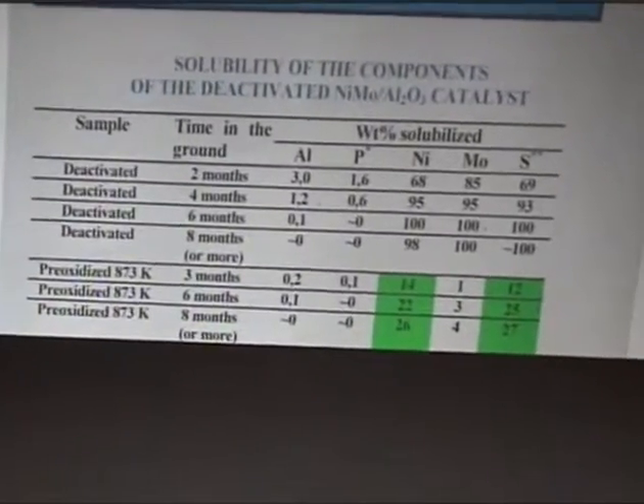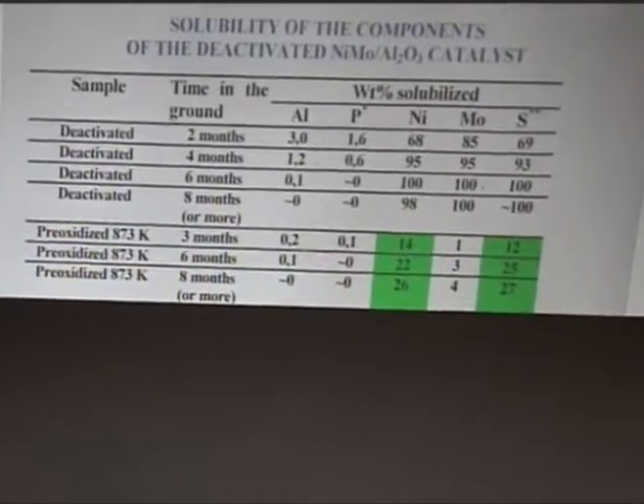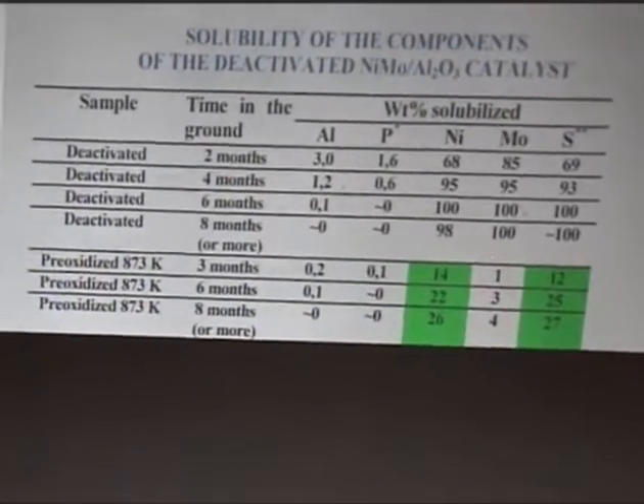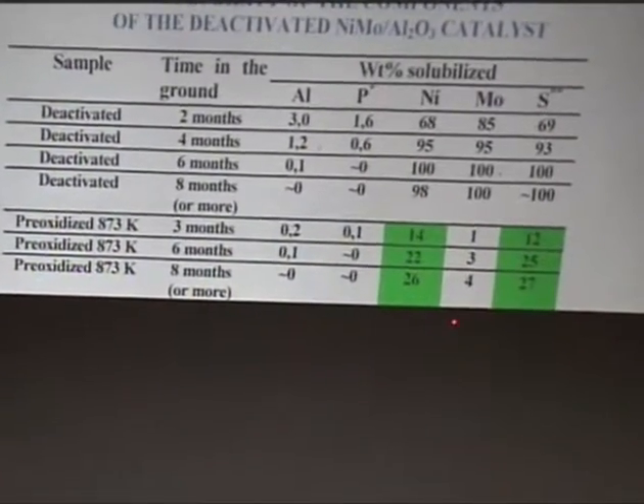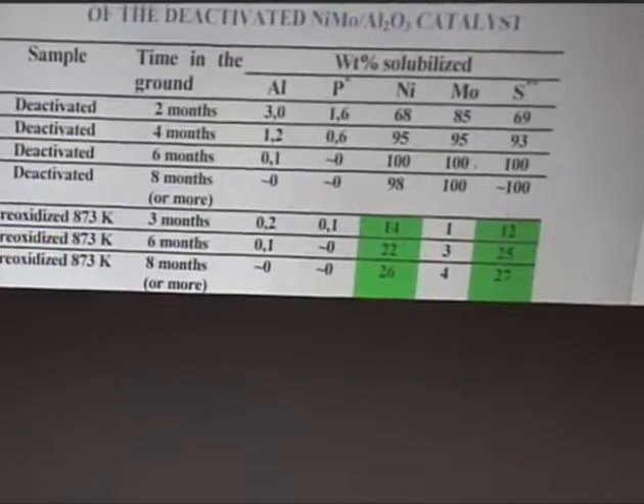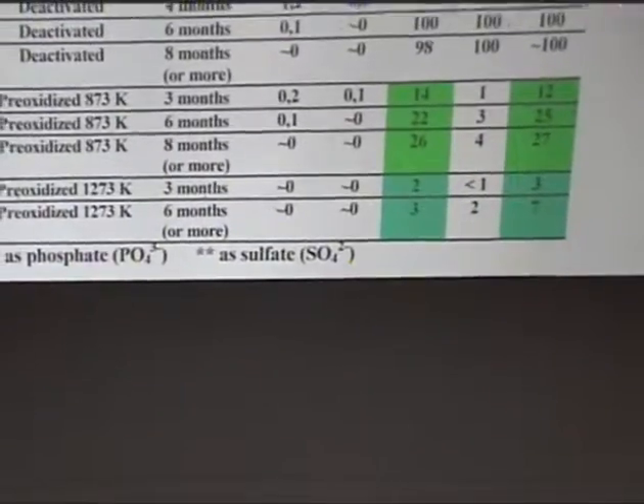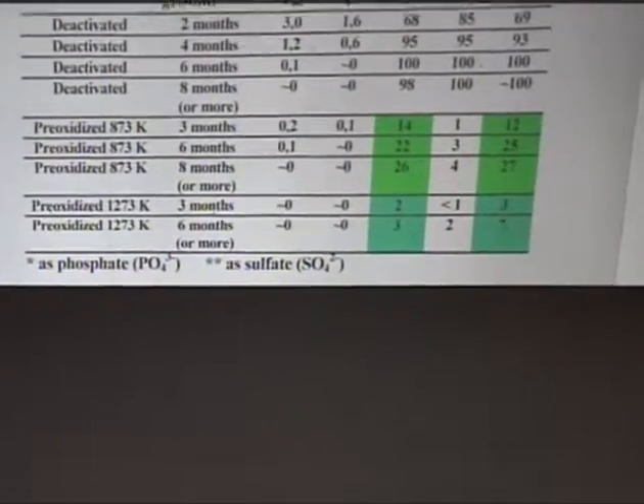When the catalyst was preoxidized at 873 Kelvin, again, aluminum and phosphorus become fully insoluble along the time. A drastic decrease in solubility of molybdenum was achieved. However, the solubility of nickel and sulfur was still important after 6 months, more or less, in the ground. More or less one quarter of all the nickel was still dissolved. And when oxidation was performed at a high temperature level, the final solubility of nickel and sulfur as a sulfate species cannot be neglected, but reached a much lower level.